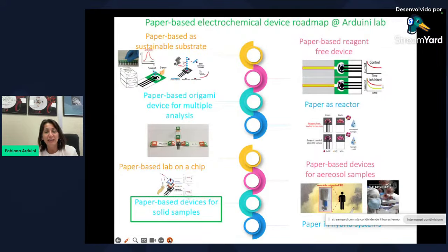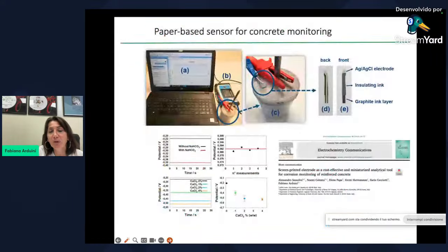And after demonstrating that it's possible to use paper to detect the target analyte in aerosol without any additional sampling system, we demonstrate this also for solid samples. An example is concrete monitoring, so a little bit different. In this case, this is again the starting point. We demonstrate that it's possible to evaluate the corrosion of the concrete structure by measuring the potential between the bar and the reference electrode. In the classical method, so the method used now, they use a wet sponge and they use the bulk copper sulfate electrode as a reference electrode.